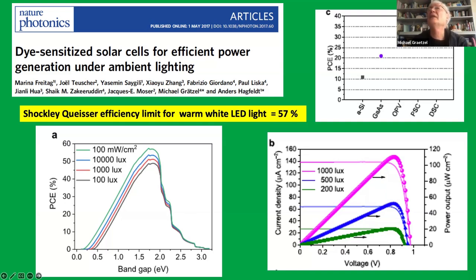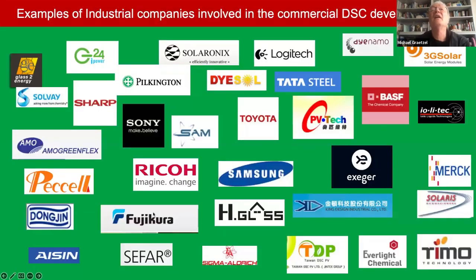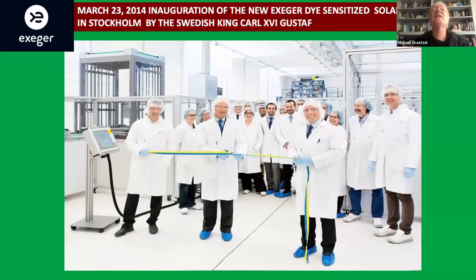And the DSCs are on top. They have reached the highest efficiency amongst the emerging and also conventional photovoltaics. You see alpha silicon, that's amorphous silicon, is much lower. And crystalline silicon would be even lower because it doesn't have the right band gap. You see, the optimum band gap is 1.8 eV. With a sensitizer, you can easily get to this absorption threshold, but silicon has too low a band gap, and so the efficiency falls very steeply when you go to the right.